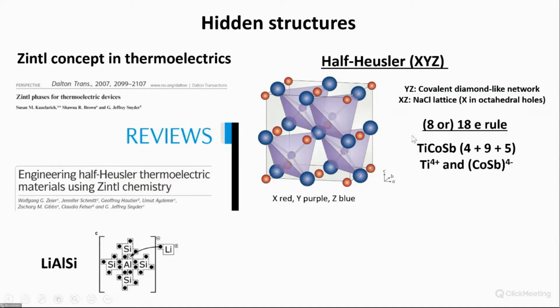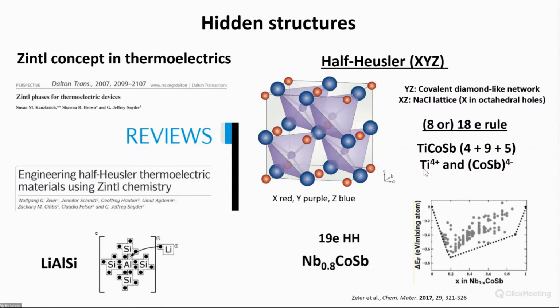And if we have transition metals in there, we have the 18-electron rule. So for titanium, cobalt, antimony, you'll have 18 electrons this way. So you have a negative framework and a positive titanium atom. Now, of course, in thermoelectrics, people will say, okay, you say the 18-electron rule, so what if I give it 19 electrons? So I put niobium in there. And then the structure comes back, at least that was the initial thinking: no, I don't want 19 electrons. I want to be a Zintl phase, so I just make vacancies. So I have 0.2 or 20% vacancies, and then I can still follow my 18-electron rule.